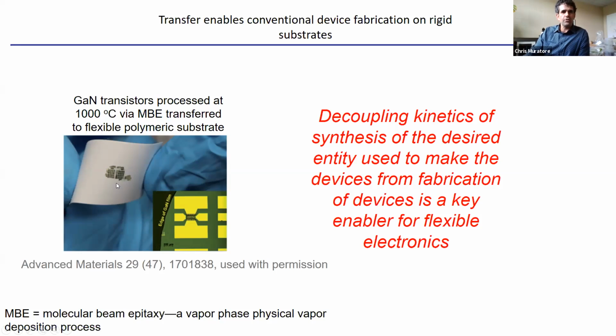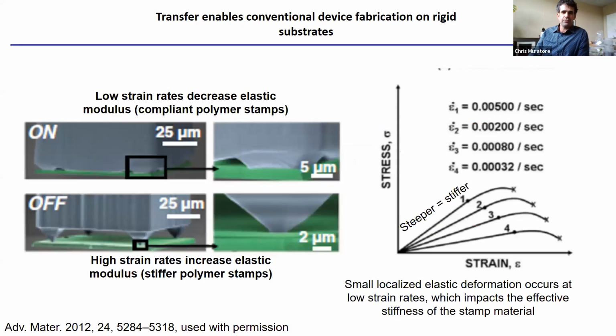But what you can do is grow it on a perfect substrate, do everything you need to make great GaN, and then just tear it off of that surface and stick it to a polymer substrate. And we'll show you some results of what happens when you do that. But this idea of decoupling the kinetics of synthesis and fabrication from the substrate is a valuable one, and transfer is kind of necessary to do that.